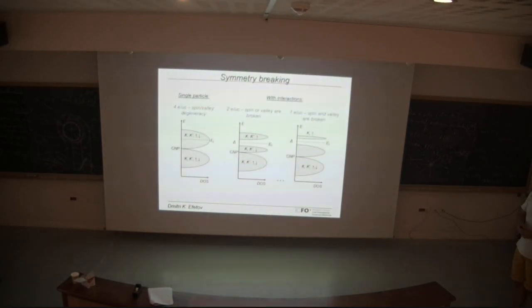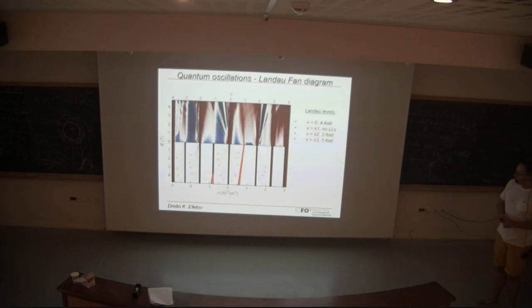One more thing, which I will probably not discuss in too much detail: in transport we also like to apply really high magnetic fields and measure Shubnikov-de Haas oscillations, which typically give us some idea of the underlying Fermi surface of these structures. For example, this is typical quantum oscillation data, again Shubnikov-de Haas oscillation data which we're taking.